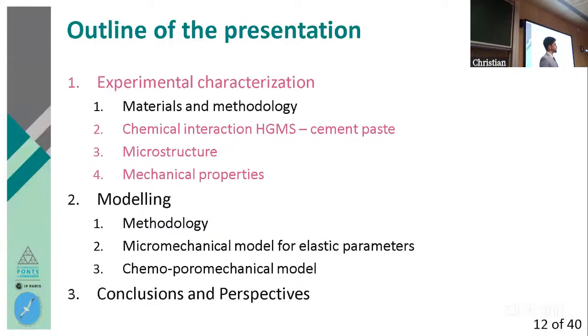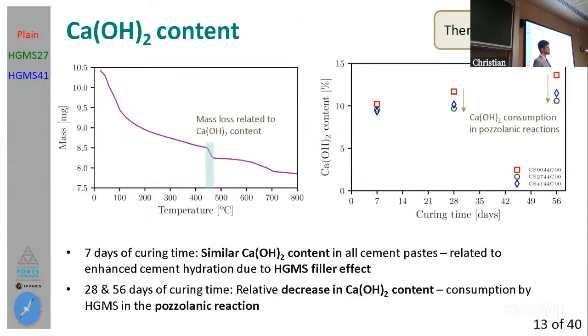After this is taken into account, I'm going to present you now some of the results obtained in this first experimental part. I will begin by analyzing the chemical interaction between the spheres and the cement paste. For this purpose, we will begin with the thermogravimetric test, in which I was able to measure the content of calcium hydroxide. To have an idea of the test, it's just a test in which we measure the change in mass of a little sample as temperature increases from around 20, room temperature, to 800 degrees centigrade for the apparatus that we had.